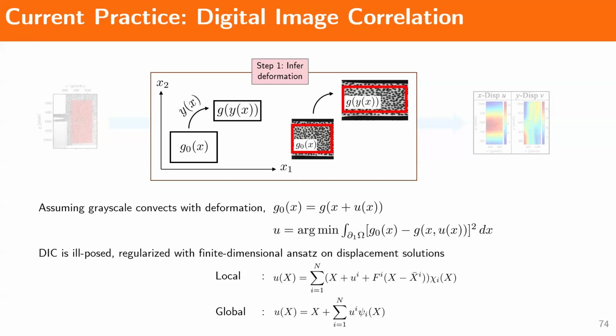So for this local ansatz, basically the idea here is that you take your images and you divide them into multiple subsets, into smaller and smaller subsets. You're basically saying, okay, my deformation is going to be affine within that subset. And then you're tracking the center of that subset, the displacement at the center of the subset here. And then the rest of the subset is basically an affine deformation. And then for the global DIC, basically you're saying, okay, my displacement field is going to be a linear span of all these global basis functions. So there's problems.